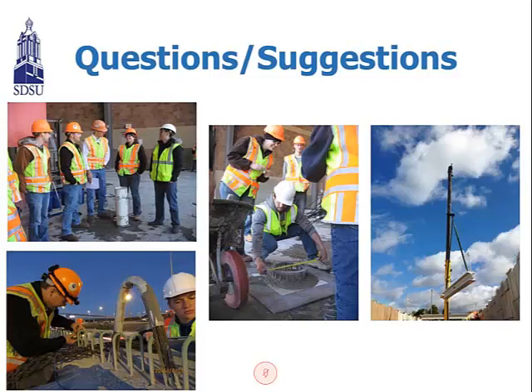The creep test, how is that performed in more detail? Did you cure that to 28 days or some certain amount of time and then apply a compressive strength equal to the design compression? How is that test done for the creep testing? Let me try to remember. I think we decided on the load. I think 2,000, 2,000 for compressive forces to apply the creep to the creep cylinders.